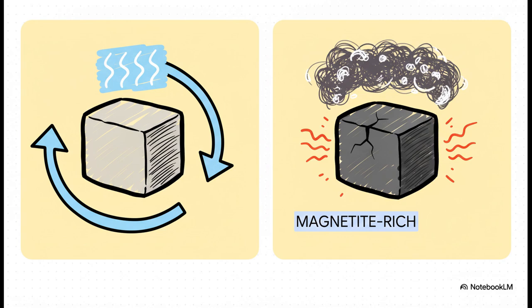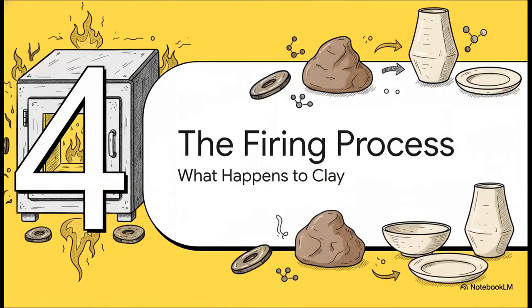Okay, so they basically came up with two main recipes. The one that was low on magnetite was super durable, really stable. But the one that was rich in magnetite, it had this really cool superpower. Now, it did wear out after about 10 or 15 firings, but because it had so much iron, it created a low oxygen atmosphere inside the kiln. Potters absolutely love this because it lets you create these really unique glaze effects you usually only get from a gas-fired kiln.